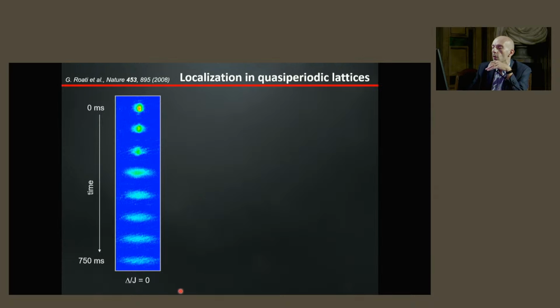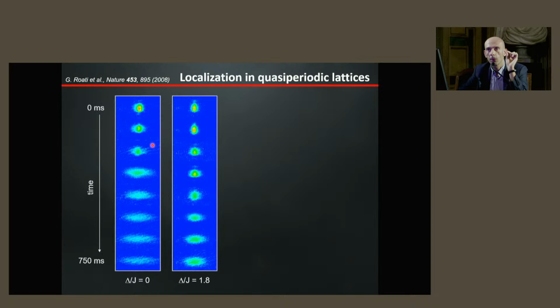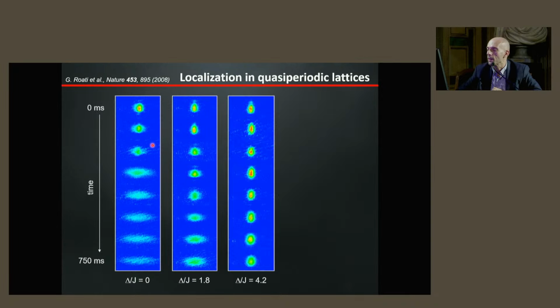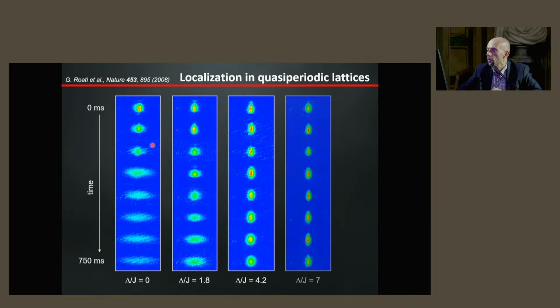So in the case of delta zero, so crystal, you have conduction, and so you have your atoms that can move, and the higher the time you wait, the more distant positions they reach in the lattice. But if you now introduce this quasi-periodic modulation...